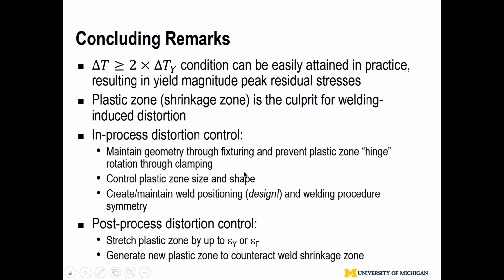That's the rotation. That means you've got to do clamping. That clamping has to be properly designed against the plastic zone, which means you need to know where the plastic zone is located. Once that gets done, this is through process planning, and then you want to make sure the plastic zone size is as small as you can, and the shape as symmetric as possible with respect to the neutral axis of the component you are working with. And then your design engineers need to consider how to position the weld. The weld has to be positioned as close to the symmetric axis, the neutral axis, as possible. And also the procedure has to be symmetric.